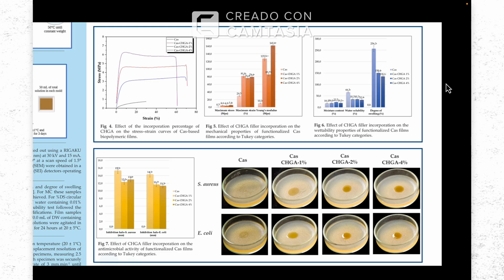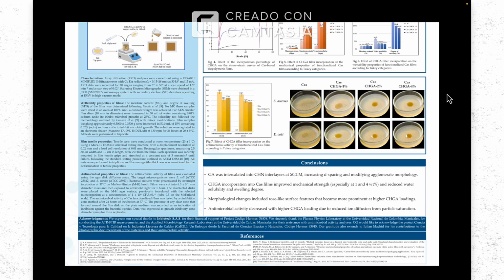Finally, we have that the films with 1% of the filler have the best antimicrobial performance. At higher loadings, this effect decreases slightly due to particle saturation that limits the copper ion release. These results show that copper hydroxynitrate functionalized calcium caseinate films combine mechanical reinforcement, reduction in water sensitivity, and antimicrobial potential.